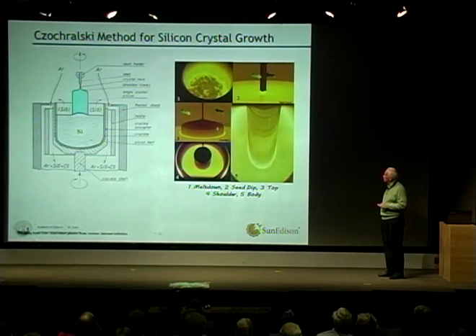We grow this part, it's called a shoulder. And then we start to grow the length down. And we control the diameter by changing how fast we pull. And so in this one, if you look carefully, you can see that there are little striae here, little streaks going around. And that's where the diameter is changing very slightly as the servo system tries to control the pull rate to control the diameter.